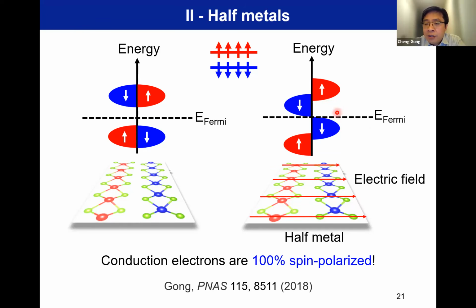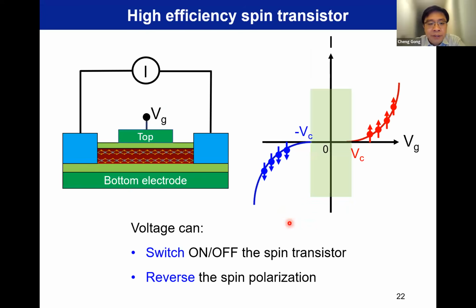All the conduction electrons now at the Fermi level are from one spin, and the other spin polarized band is still insulating. So you can leverage these 100% spin polarized Fermi electrons to develop spintronic devices. So you simply build such a bilayer A-type antiferromagnet based transistor. You can use a vertical gate voltage to create the half metallicity by applying voltage above this critical voltage. So you can use positive voltage or negative voltage to push spin up and spin down electrons into the half metallic state. So you have a switching function. You can reverse the carrier spin polarization.